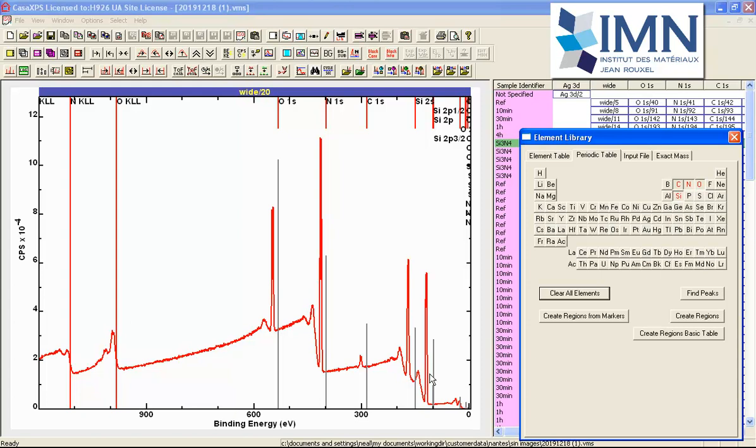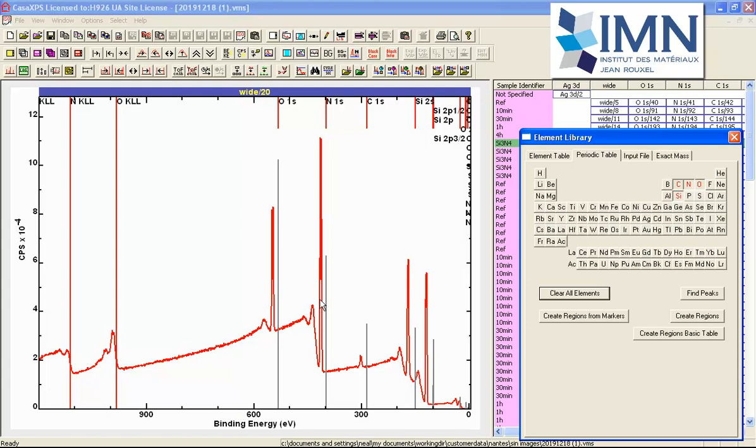While it is possible the element markers are not precise for any given material, to see such a pattern where they are all offset to the left suggests that these peaks have all lost energy. We would have expected this spectrum to be acquired with a charge compensation state where a positive charge exists. That is to say, each one of these peaks now arrives with a kinetic energy less than the expected energy for a given photoemission line.